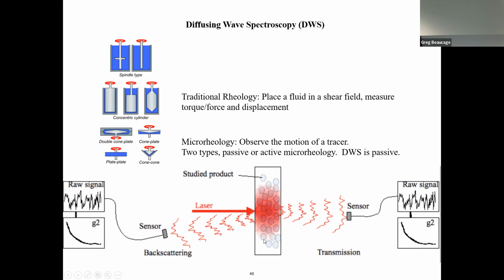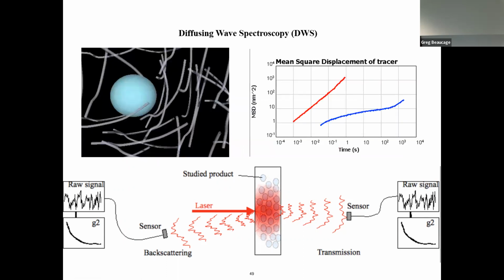If they're moving with Brownian motion, you can get the diffusion coefficient, and that's going to give you the viscosity, basically of the fluid that the bead is in, right? Because you know the radius of the sphere, so you know the hydrodynamic radius. You don't know the viscosity of the fluid at high frequency. So you get the viscosity from the dynamics, from the DLS of these beads that you put in as a probe for the thing, right? So you stuff in beads and you watch that motion. Then this is showing that basically there are two kinds of motions that beads can have.